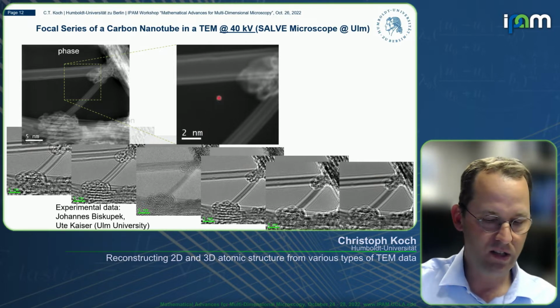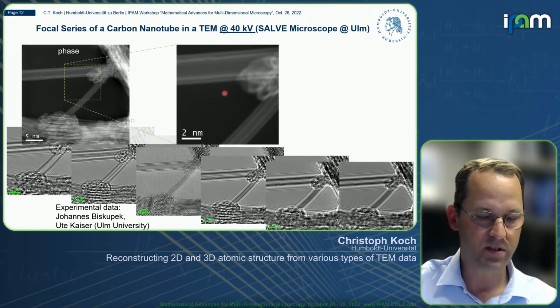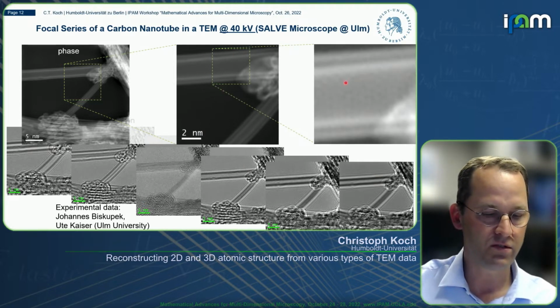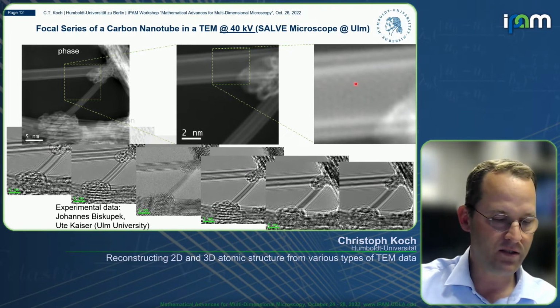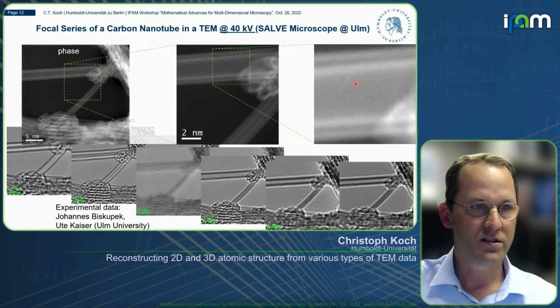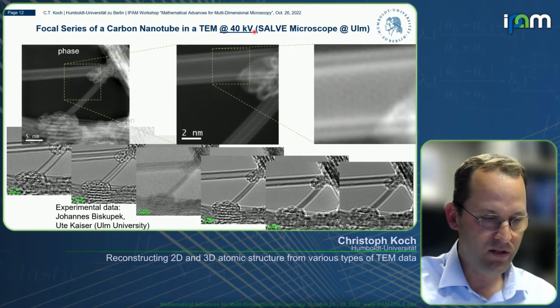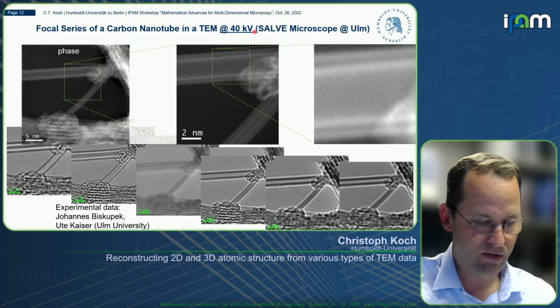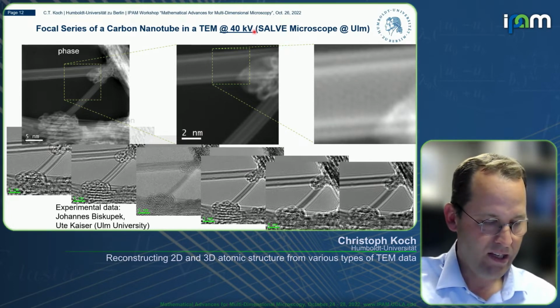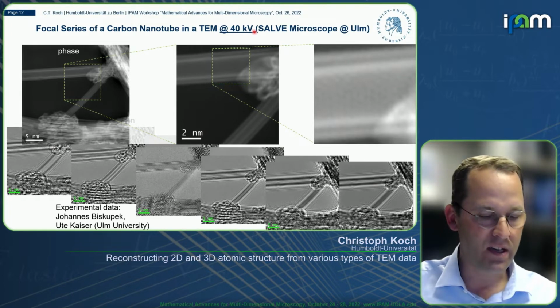And if you zoom in, you can now see it also recovers the atomic resolution structure of this double-walled nanotube, despite the fact that your wavelength is actually quite long, because you have a very low accelerating voltage. And this data was actually provided by colleagues in Ulm, it was not acquired by our own group.